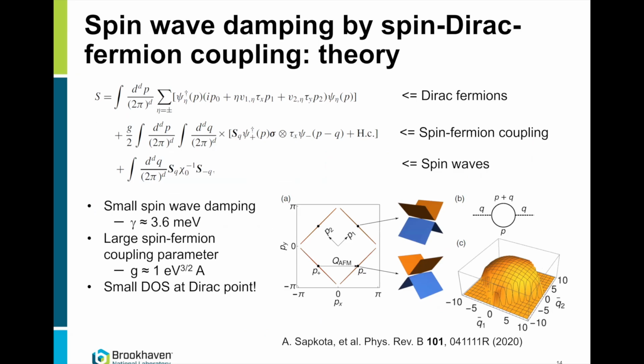We also understand theoretically the reason that the damping is so small, and that is because there are very few of these Dirac electrons. The density of states in the Dirac cone is very weak. So our theorists were able to put together a simple model of Dirac electrons coupled with spin waves. With a very large coupling constant, we can actually explain the very small damping. So again, the coupling is strong, but the density of Dirac electrons is weak. In fact, what this implies is that if you would indeed be able to create this canting, we would have substantial influence on Dirac electrons. We would create Weyl points. We haven't found a material with that canting yet.